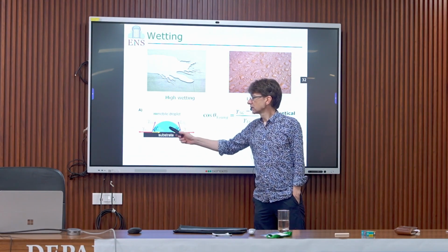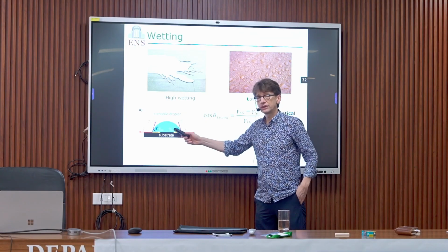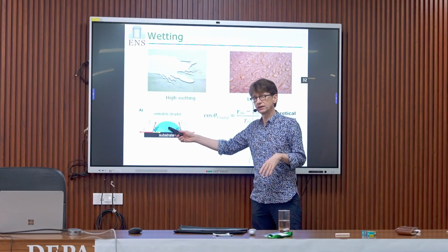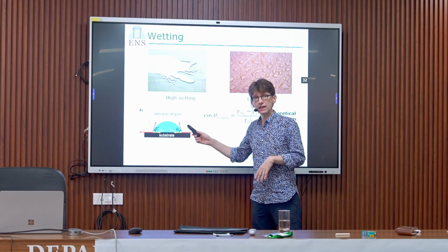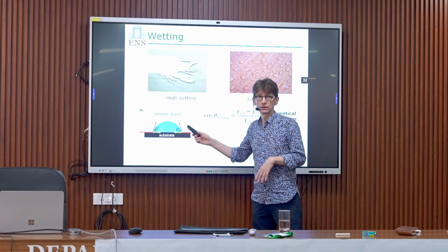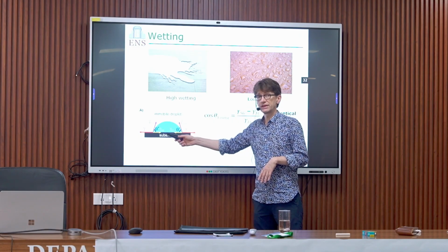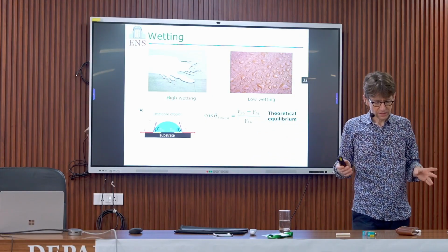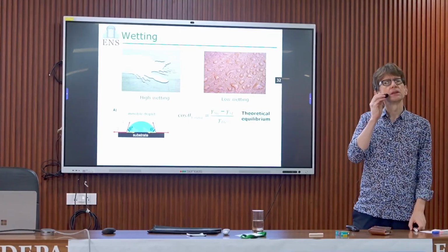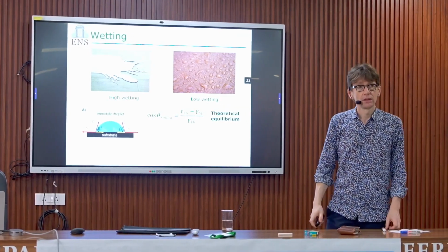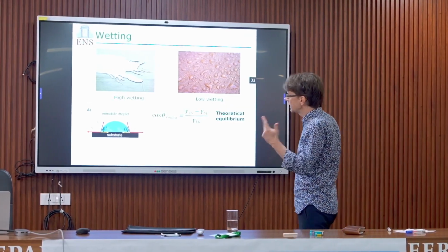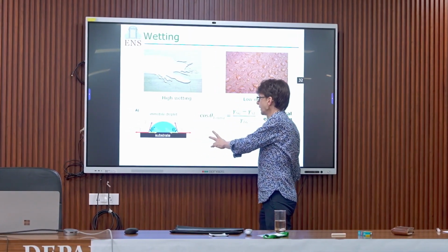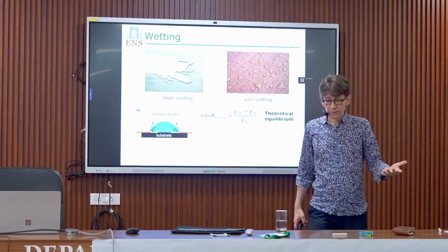So this is what you can call hydrophobic, hydrophilic, how materials like or not water. But don't forget that there is air or gas or whatever. And this component is as important as this one, plus of course the surface tension of the liquid. So it is nice to always remember that in wetting you have three interfaces to consider, and never forget the solid-gas interface.